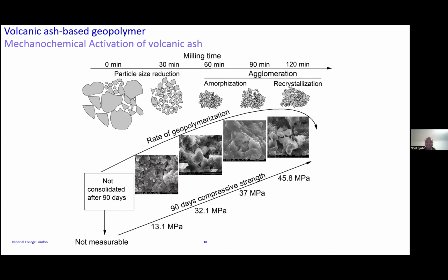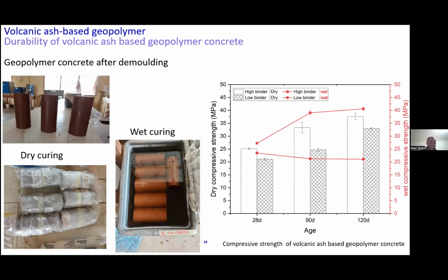But by applying the mechanochemical activation, we can see that a material that was not able to achieve any strength, that was not able to harden even after 90 days, is now able to achieve 45 megapascals after 90 days. This is quite huge. It means the products being developed here can even be used to construct bridges. You know, for bridges you need materials that are very strong. That is quite fantastic. A material that was not able to give any strength initially, by applying this process, can, when mixed with our alkaline solution, achieve much higher mechanical properties. That was very fantastic.